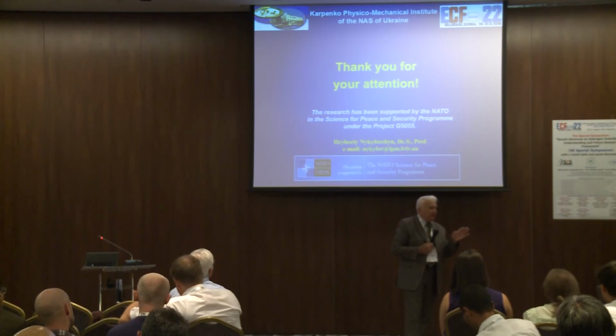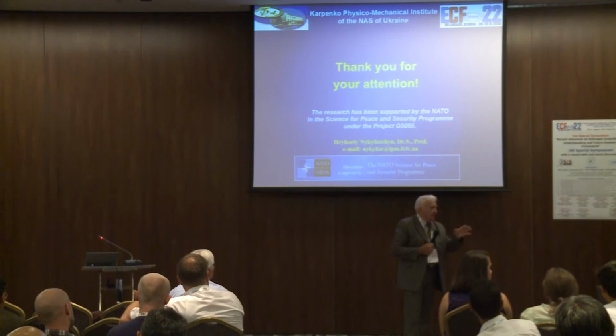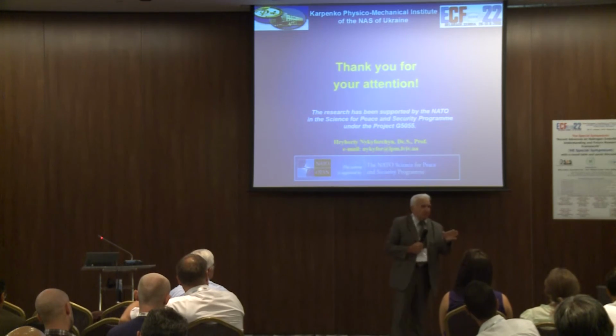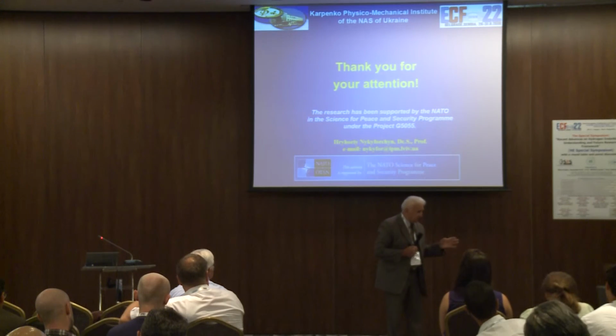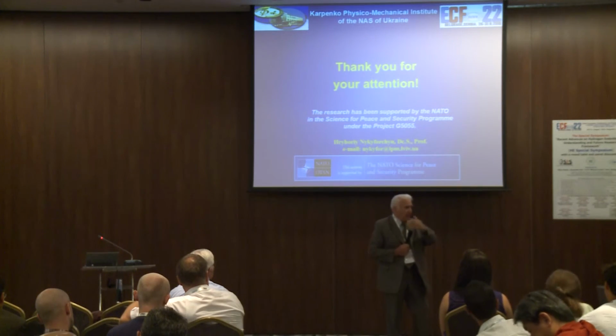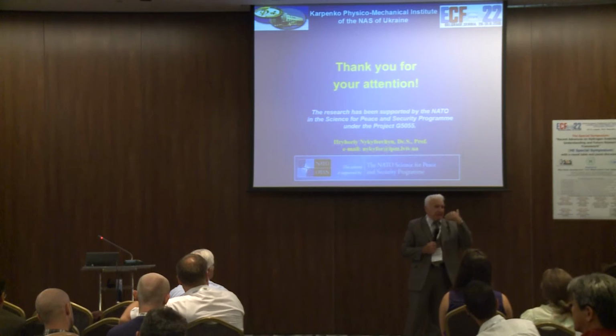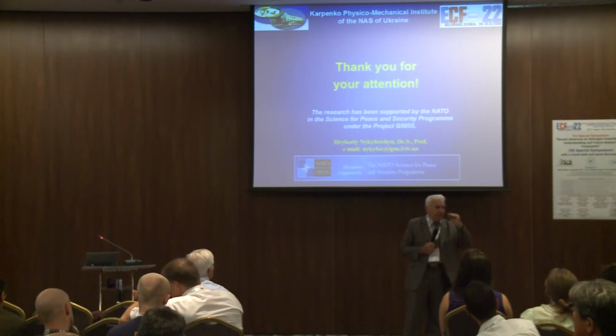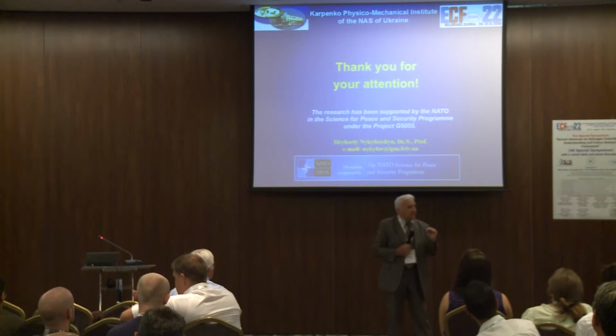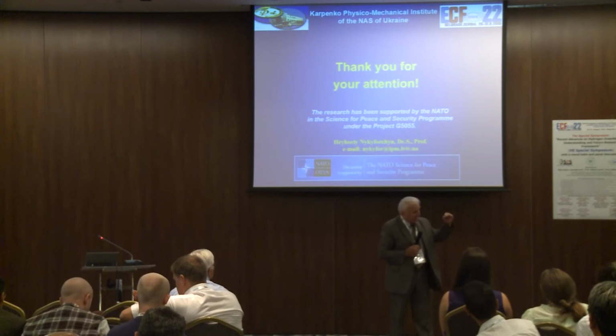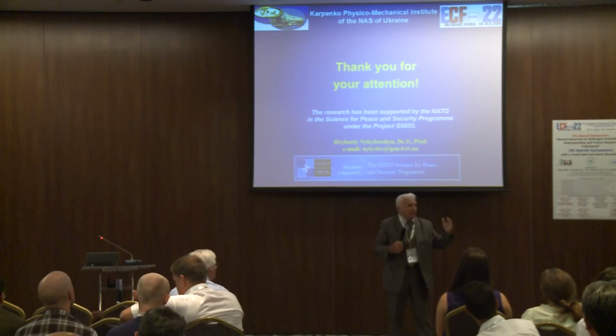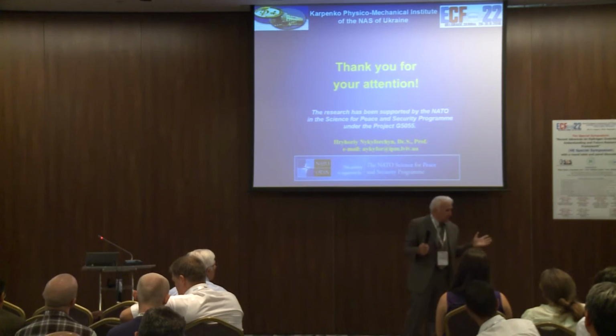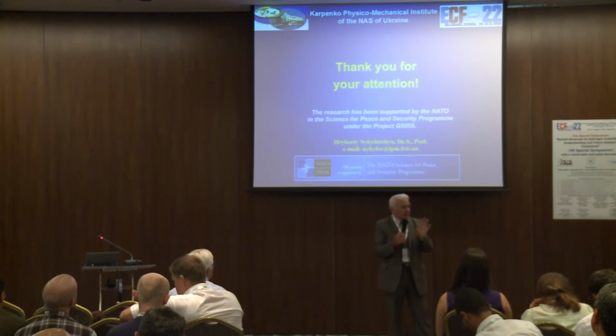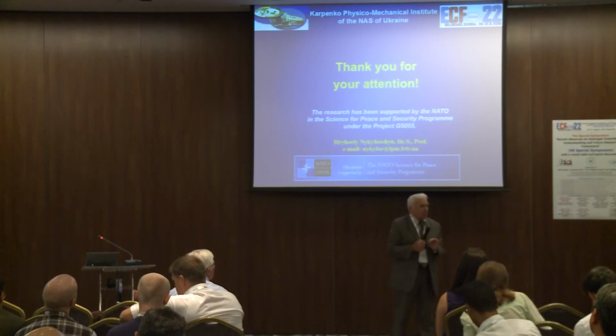It is known that, for example, high carbon steels are more sensitive to hydrogen embrittlement than low carbon steels. Therefore, if we have in local places enrichment by carbon carbide, we expect that when we have hydrogenation of the metal, we expect damage in these places. These factors are in combination.